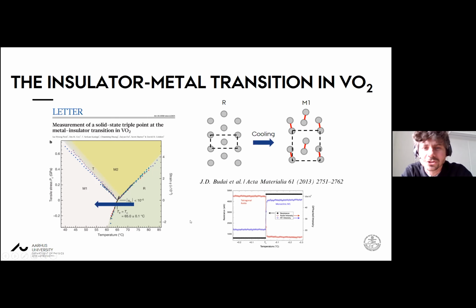Okay, so vanadium dioxide, in some sense, seems quite a simple system. We have a high temperature metallic phase, which has a near cubic symmetry. And when you cool down, the system becomes an insulator. And this insulating phase transition occurs at the same time as the structural transition, in which the vanadium ions go from the high symmetry positions, they dimerize and then they twist, and this opens up a band gap.